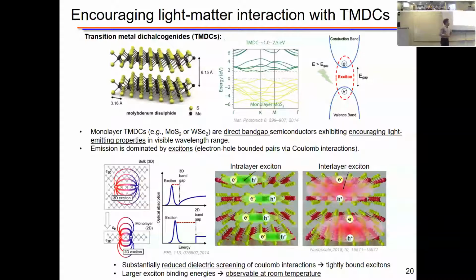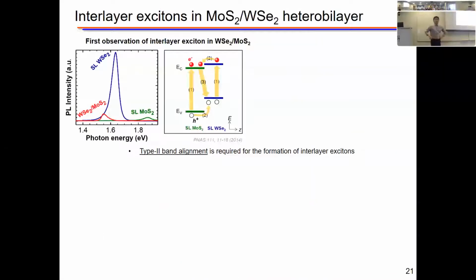Just to give some terminology here, when the electron-hole quasi-particle is created within a layer, it is called an intralayer exciton, and when it is created between the layers, it is called an interlayer exciton, which is of particular interest in our study. The first observation of interlayer excitons in the molybdenum disulfide-tungsten diselenide heterobilayer system was reported in 2014 by Xiaodong Xu's group, where they observed the emergence of a new photoluminescence peak, redshifted by 75 milli-electron volts relative to the A exciton energy of molybdenum disulfide.